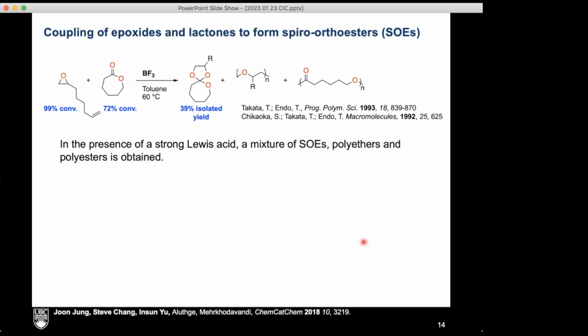So here's a very representative example with BF3, when an epoxide and caprolactone are reacted with each other one-to-one. And in this reaction, first of all, not all of the caprolactone is consumed, all of the epoxide is consumed. We get about 40% of the spiro orthoesters, but we also get polyether and polyester because this is a Lewis acid. A Lewis acid is going to polymerize everything. And so the fact that we get spiro orthoester is not surprising. The fact that we get only spiro orthoester is surprising. So that is a really important function of our catalyst system.